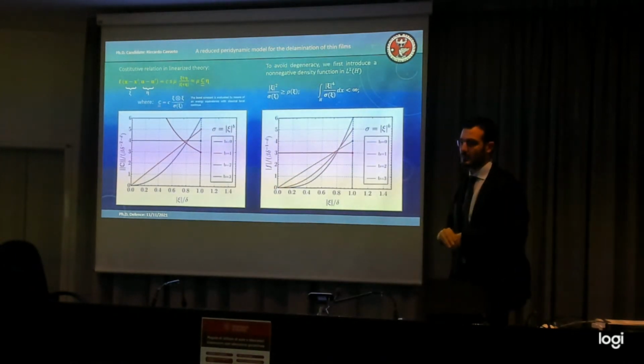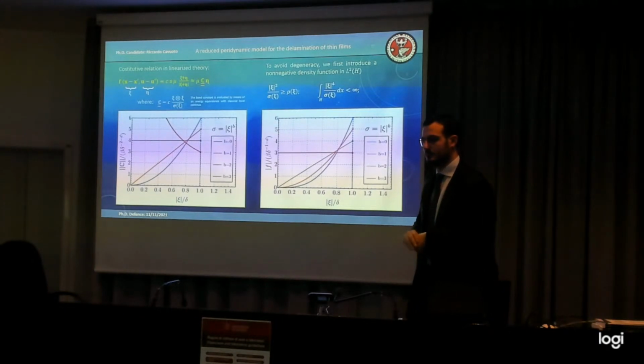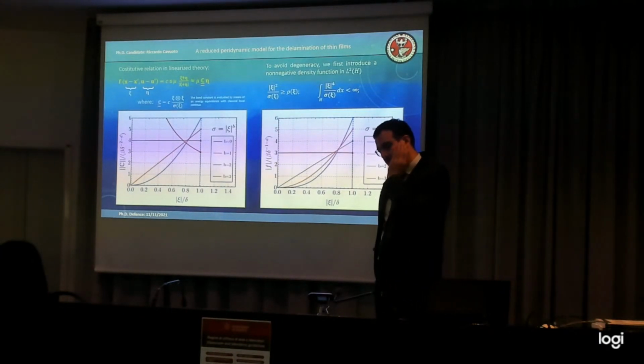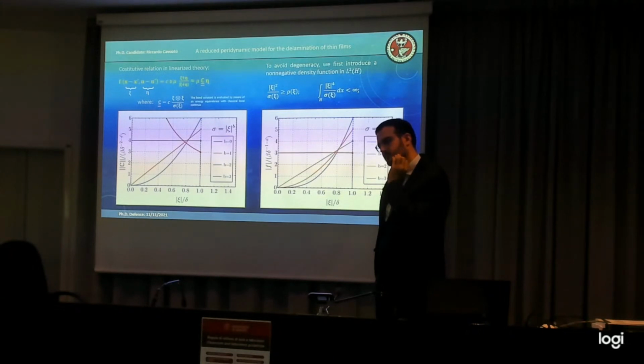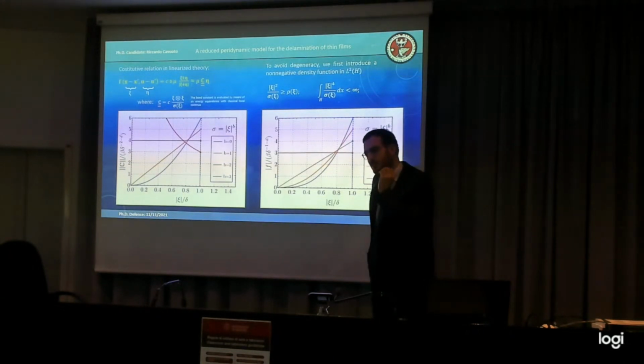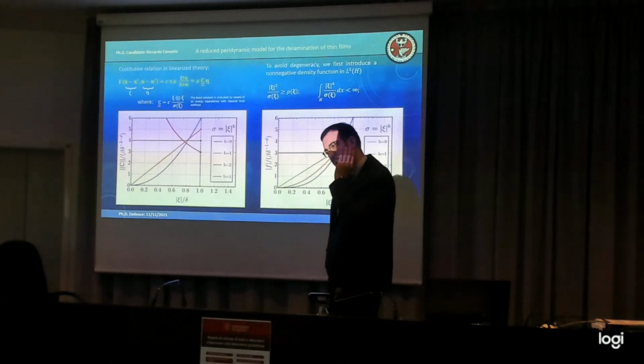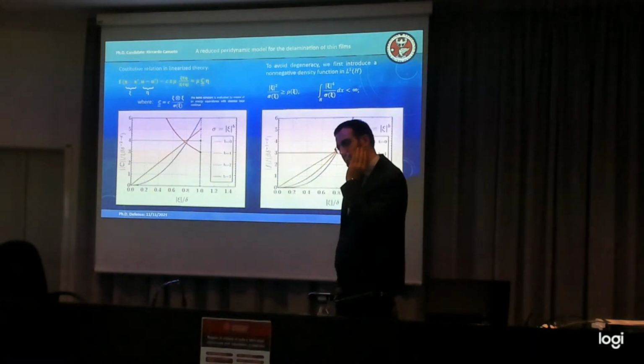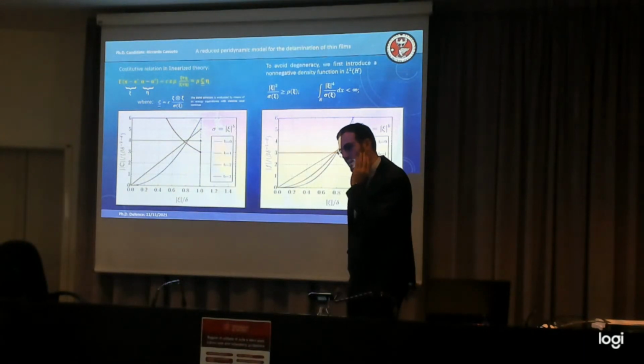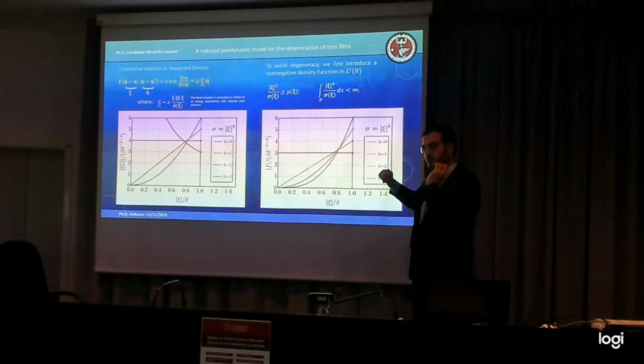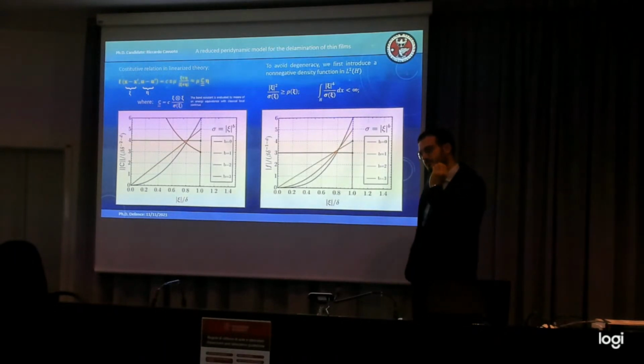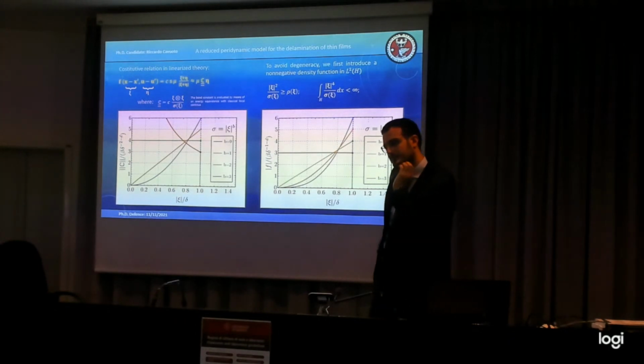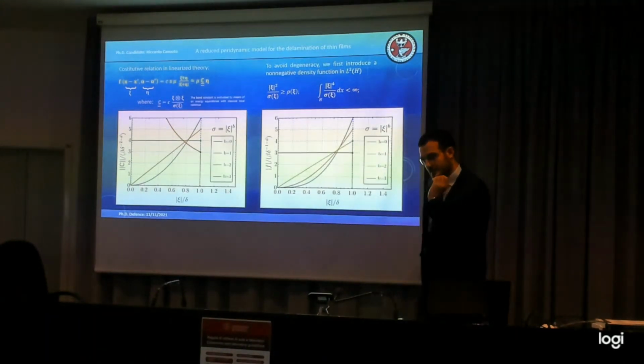Okay, yeah. And in this case, the crack path, the direction of crack propagation, is determined by the link breakage. Yes, it's not immediate. Then do you recover, for instance, a classical crack propagation criterion, like the maximum stress criterion for the direction of propagation? Does it recover some classical criterion as the delta, the nonlocal parameter, goes to 0, or even for a finite value of delta?